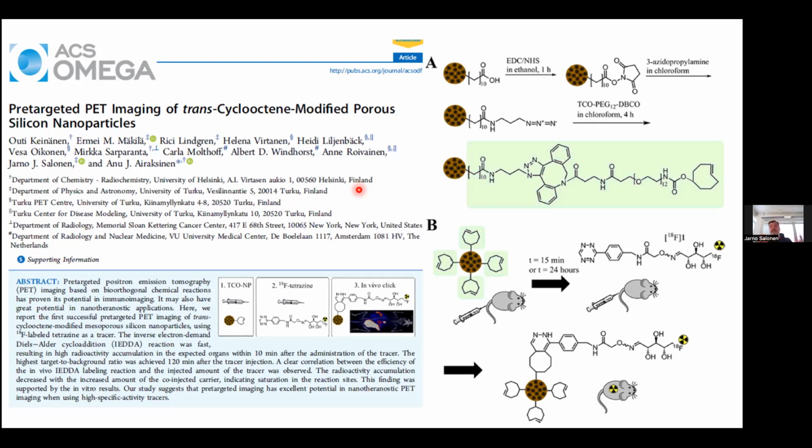So now we have solved the problem so that for nanoparticles, we do thermal carbonization when the porous silicon is a freestanding film. Then we mill it. So during the milling, we create a small amount of new oxidized areas in our nanoparticles, which initiate dissolution.